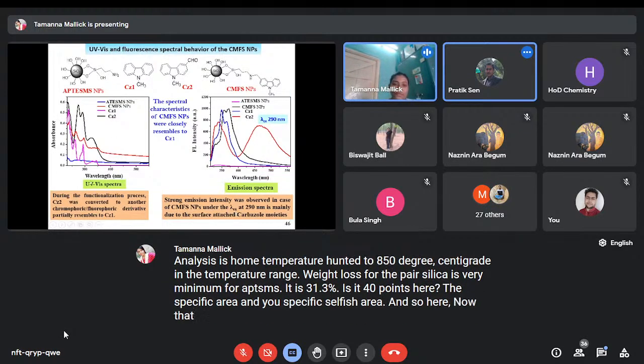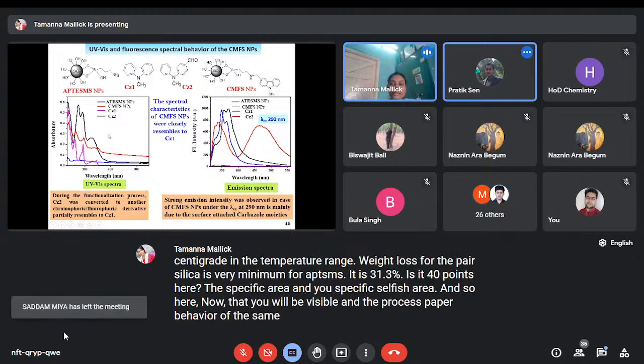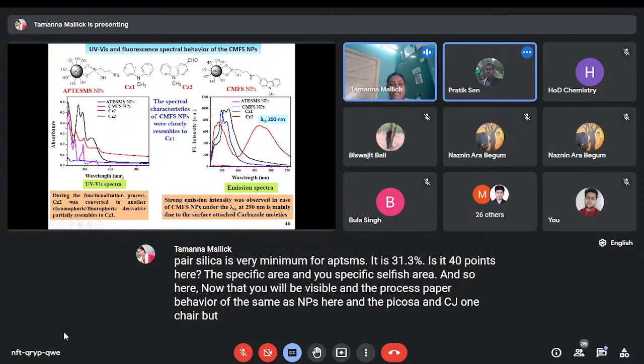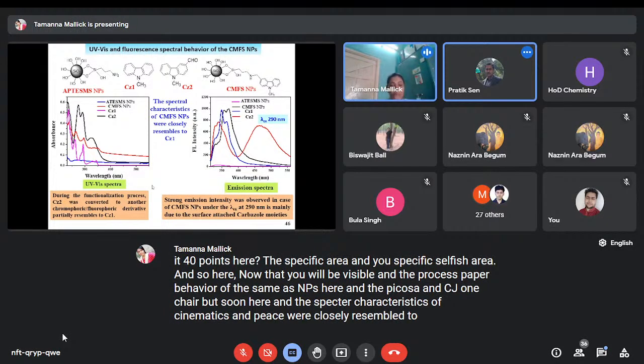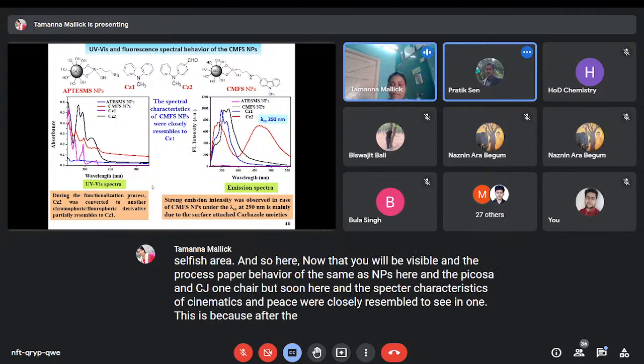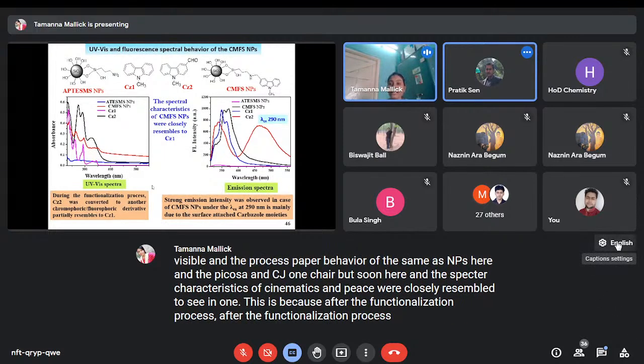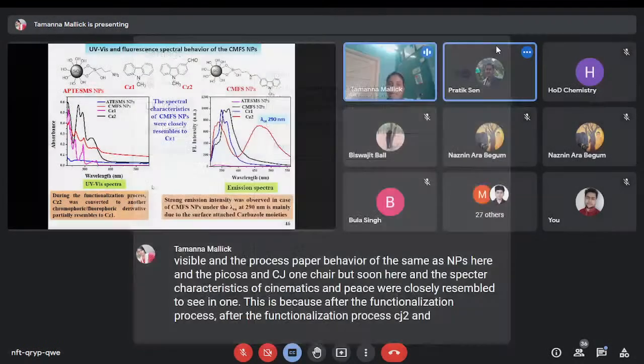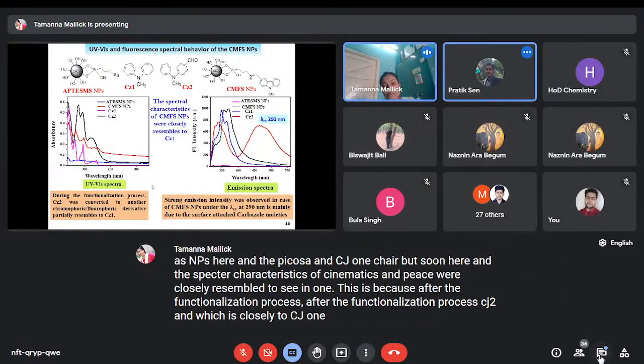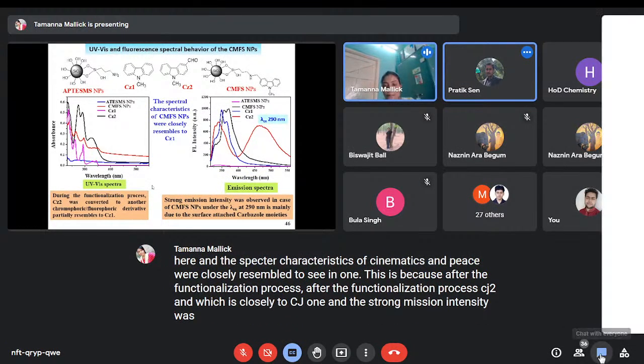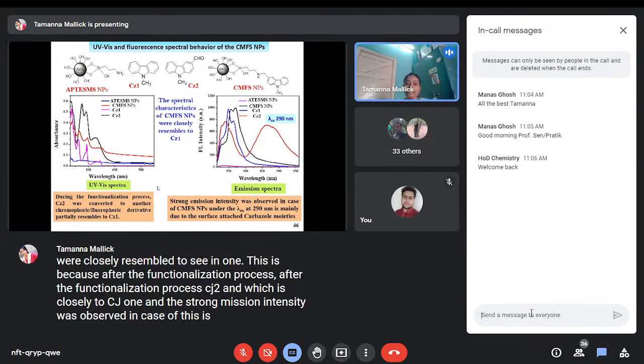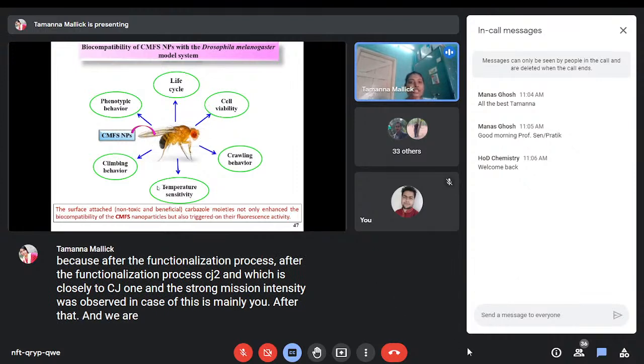Now, the UV-visible and the fluorescent spectral behavior of the CMFS NPs, the precursor and CZ1 are shown here, and the spectral characteristics of CMFS NPs closely resembled CZ1. This is because after the functionalization process, CZ2 converted to another fluorophoric moiety, which closely resembled CZ1. Hence, the strong emission intensity observed in the case of CMFS NPs is mainly due to the surface attached carbazole moieties.